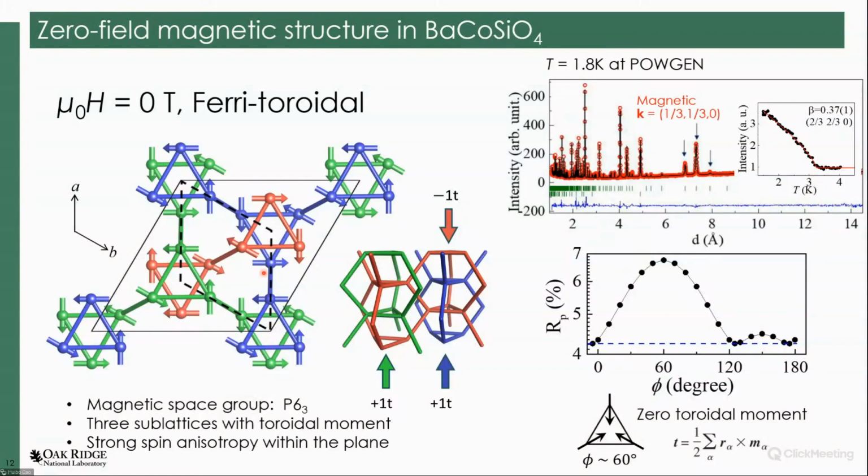What we found is, if you look at different colors, different lattices, the collinear antiferromagnetic coupling is between triangular lattices in different layers. By connecting those lattices, we can get three sublattices. Those are the first nearest neighbors. We expect the interaction to be strong, but because of frustration, they form this 120-degree magnetic order. The other interaction is a perfect antiferromagnet, also strong, with not much frustration there, so they can stabilize in a happy position. With just these two interactions, we can connect the whole magnetic lattice in the crystal. Then we get the different colors. That's how we understand the structure we got from magnetic solution by neutron diffraction.